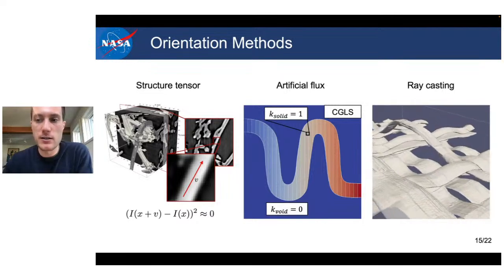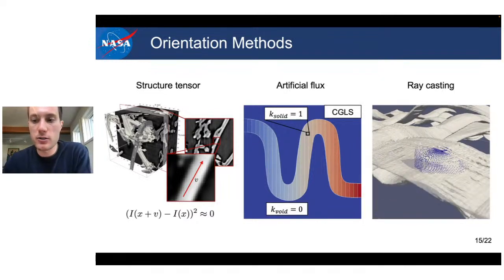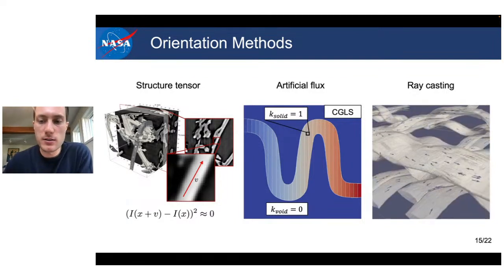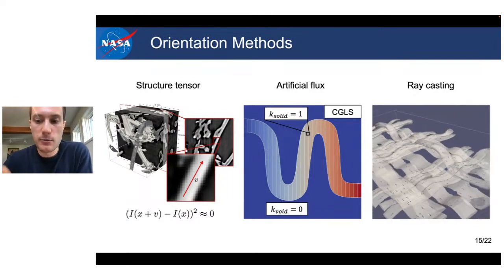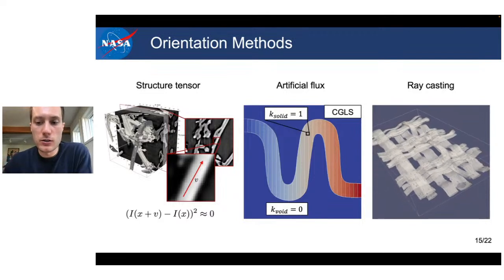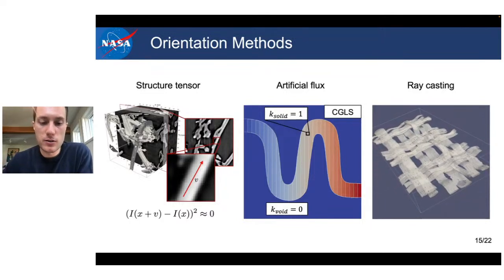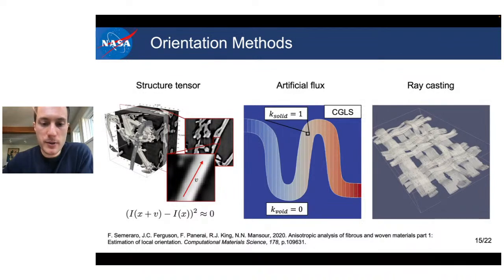And then finally, there is the raycasting, which uses the particle method that I mentioned earlier, where you track the longest traveling particle and pick that to be your local approximate orientation. So we've wrapped up this work into a part 1 paper to Computational Materials Science. The part 2 actually was about the conductivity, which uses the local orientation of these phases.